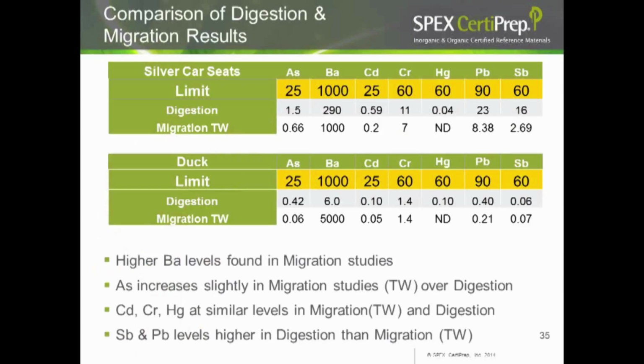If we look at a comparison of the digestion and the migration results, here we have our silver car seats. For the digestion, all of the results actually do fall under the limits, but the migration shows that the barium actually migrates and up to the limit for those silver car seats. Our friend the duck, the barium levels in the migration seem to be very high, but all the rest of the results fall within limits.